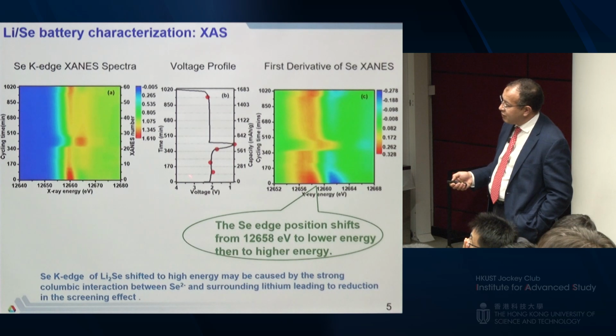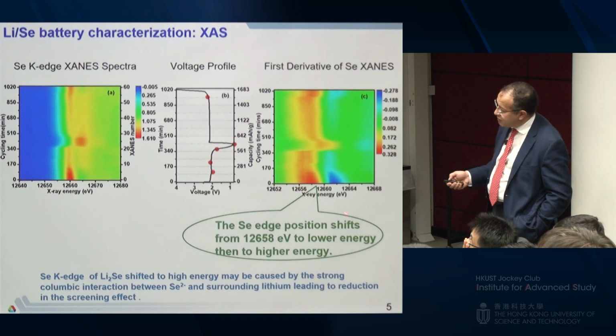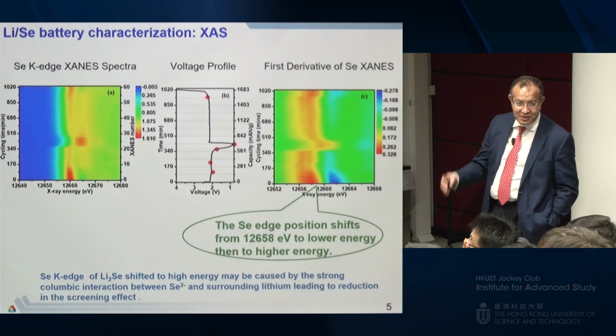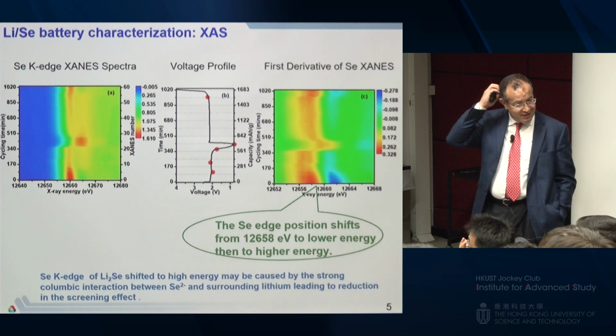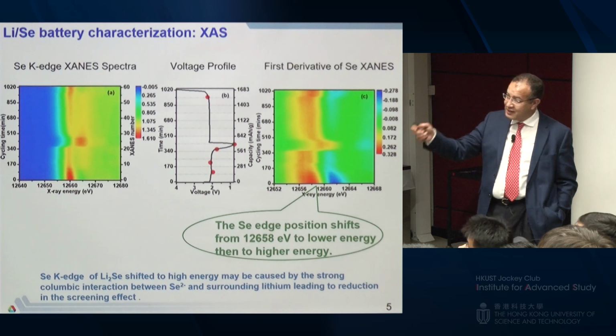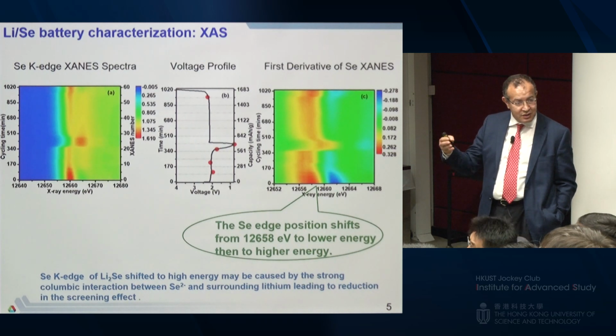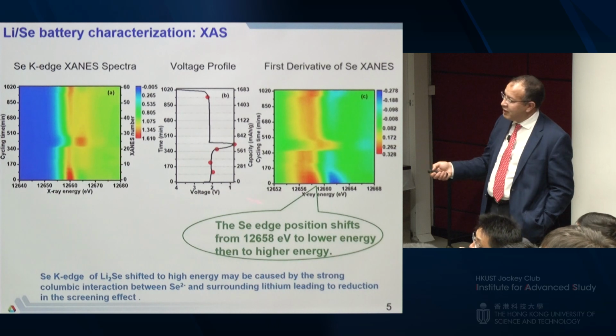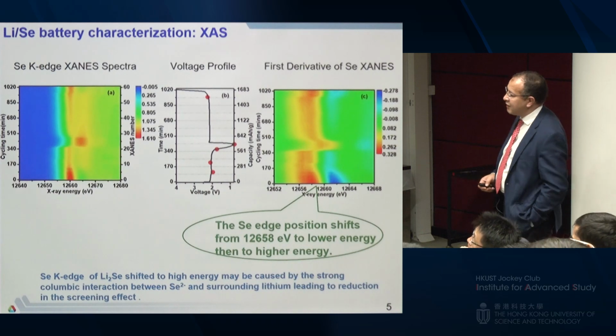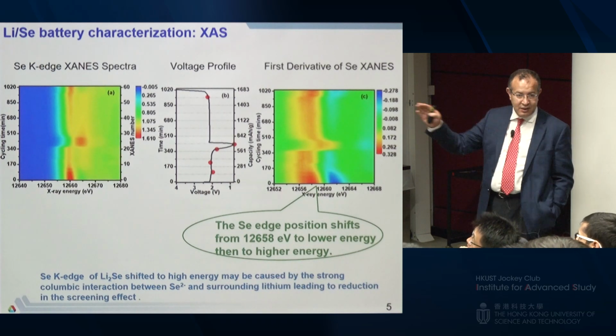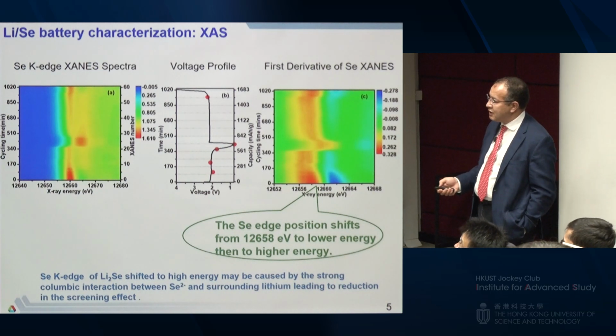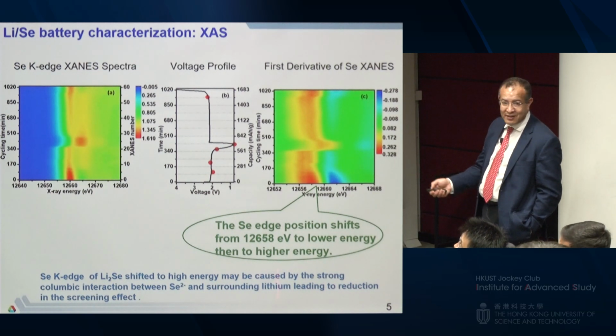So you can see when you do that, during discharge, your XANES spectra is shifting toward low energy, which means you are changing oxidation state. You're reducing, you're forming this polyselenide. And these are probed in the electrolyte. So there is a dissolution happening where the oxidation state of these different phases can be clearly seen here. If there is no oxidation state change, it should be flat.